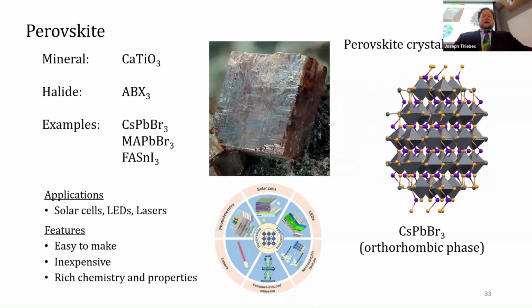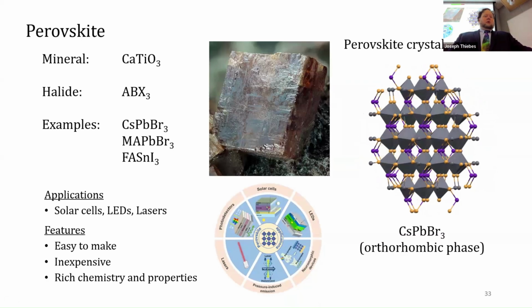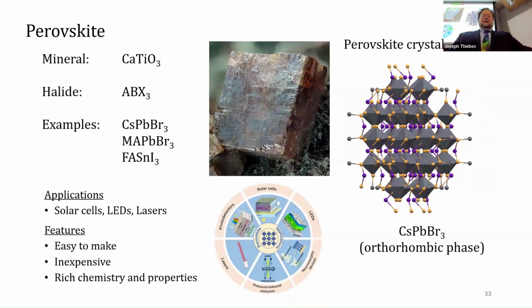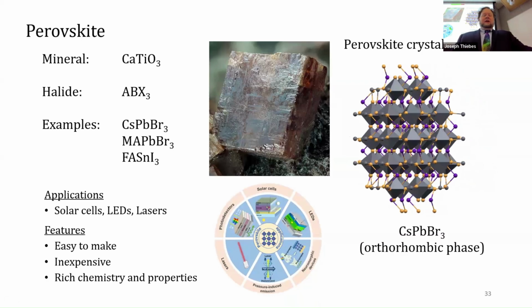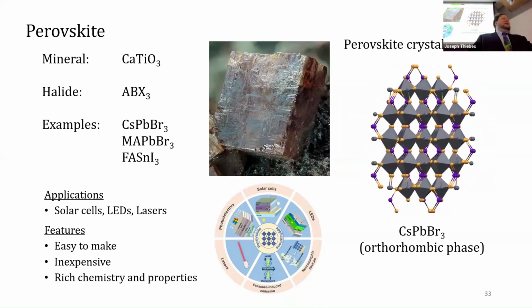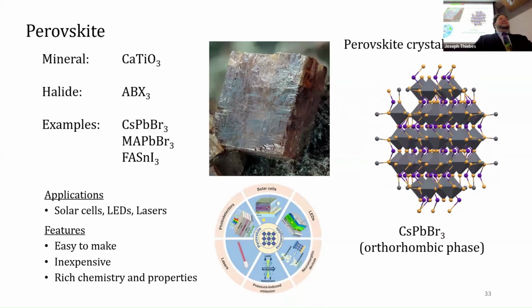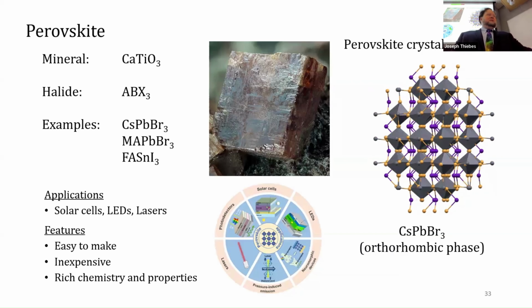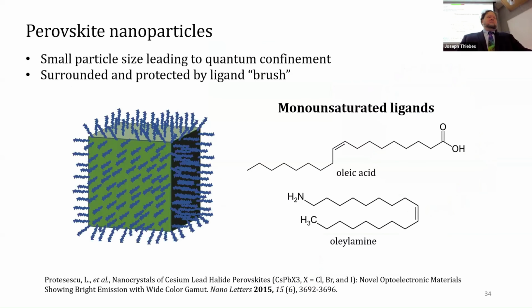And the only problem with perovskites is that they are sensitive to degradation by things like water, oxygen, and sunlight. Maybe a little bit of a problem for solar cells. But perovskite nanoparticles can address this problem. The synthesis of these nanoparticles involves using ligands. This is an example of the kind of molecule you can use as a ligand.